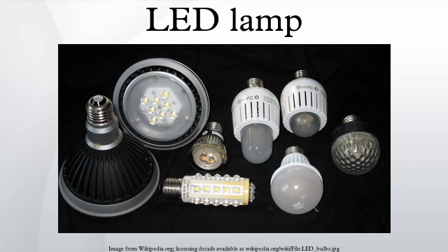Because of this increased heating at higher currents, high-brightness LEDs have an industry standard of operating at only 350 mA. 350 mA is a good compromise between light output, efficiency, and longevity. Early suspicions were that the LED droop was caused by elevated temperatures.